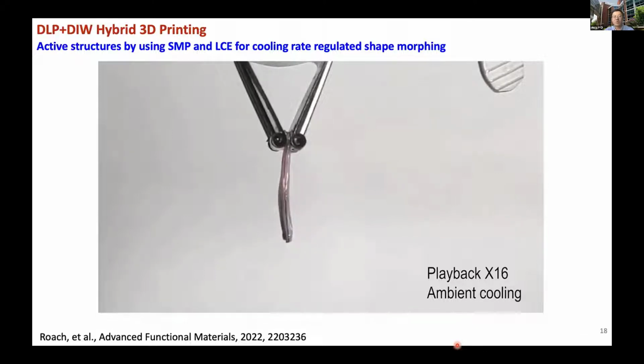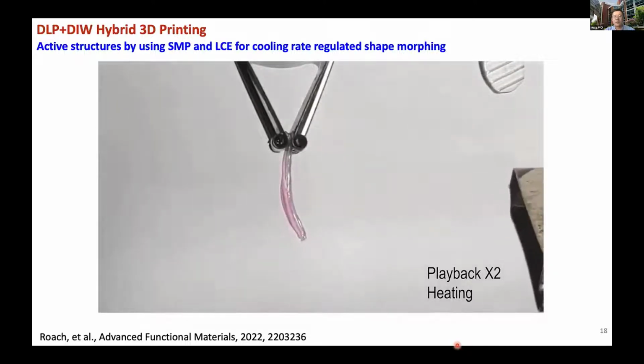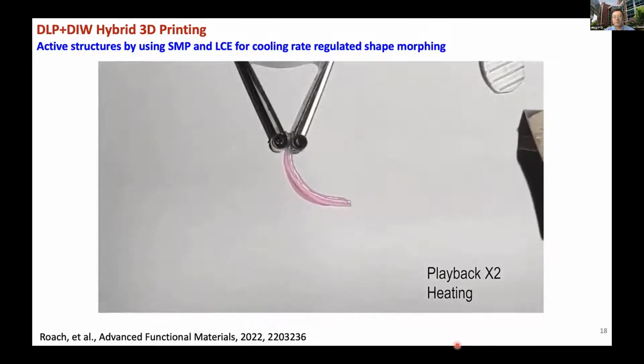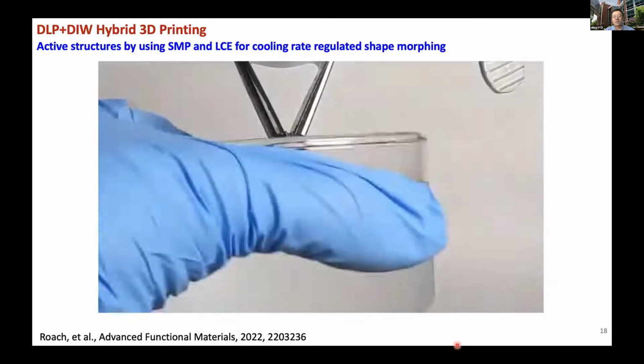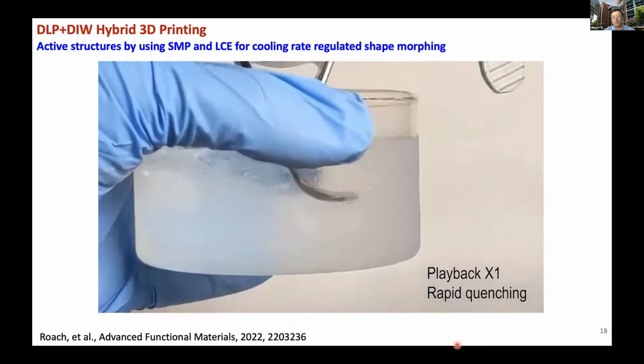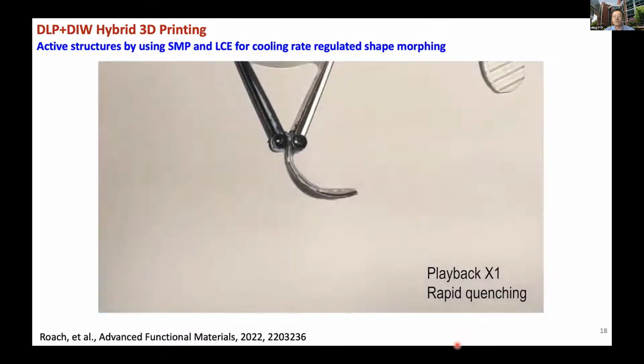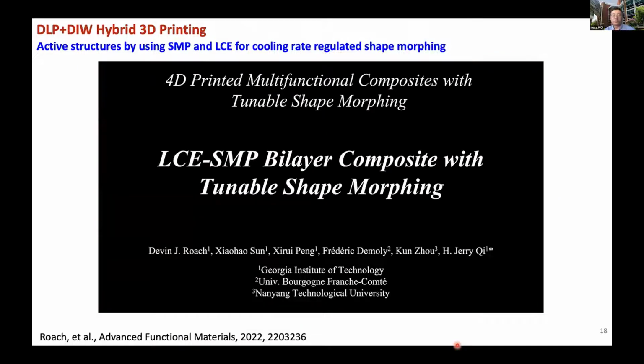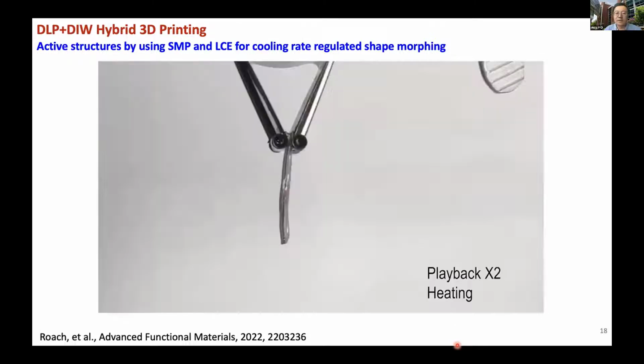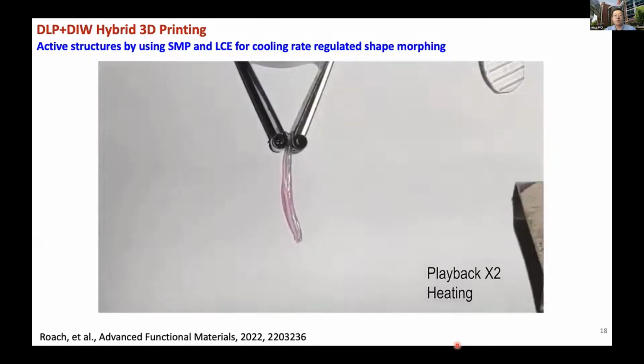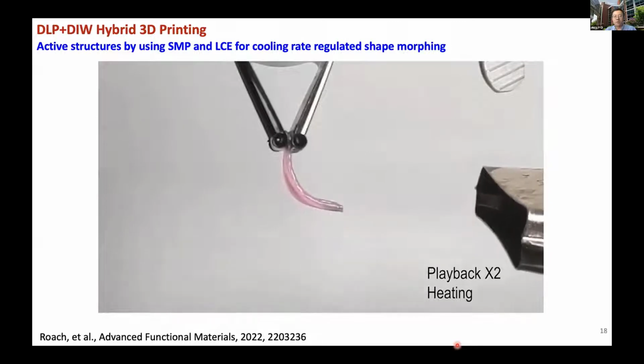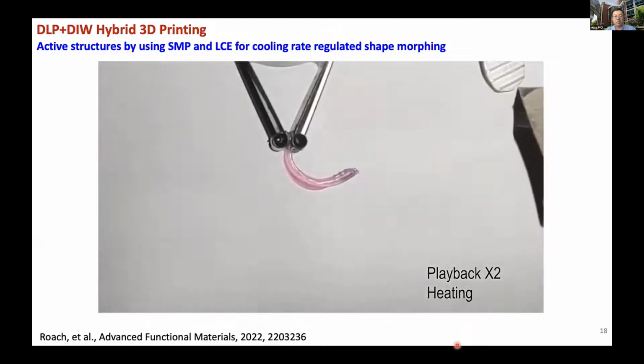With ambient cooling, you can see here the beam gradually becomes straight. So now I heat it up again. Now you can see the bending. Now I put it in the ice water, and you can see my structure just being fixed in that bent shape. If you heat it up again, it would just come back again. So you can do this reversibly, depending on where you want to go. You can control the heating and cooling history, and you can obtain different shapes.